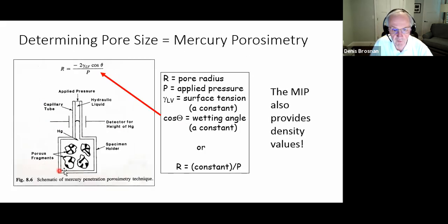To determine pore sizes, we put fragments of the ceramic in a chamber that's pressurized, usually containing mercury. You can use helium for very, very small pores, but mercury is used for most micron and submicron size pores. There's an equation called the Washburn equation, which relates the applied pressure that we see as mercury is forced incrementally into this pressure chamber. We can determine the size of pores that are being intruded with mercury at any particular time.